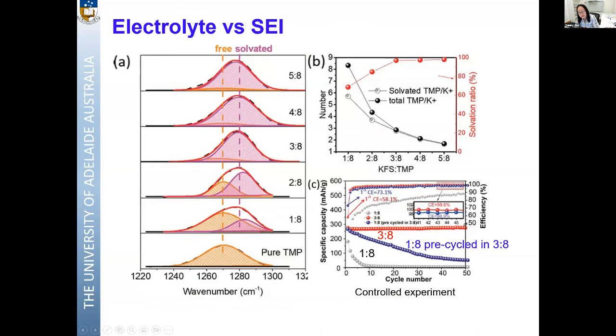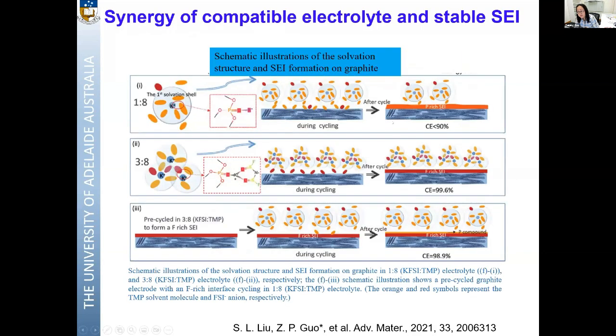So from the Raman analysis, we found that when we increase the concentration from about 3 to 8, that means about 2 m, nearly 100% of the TMP is associated with potassium ion, that means it's in the solvation structure. So there's no free TMP molecule. Therefore, the TMP won't decompose on the surface.